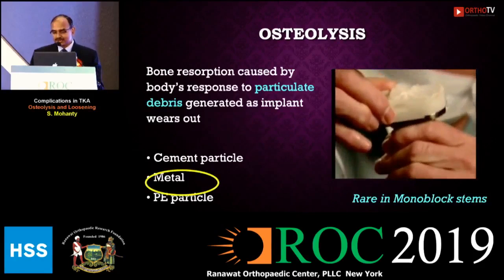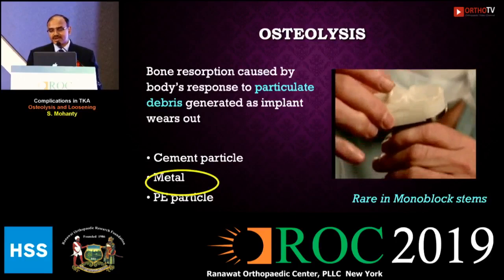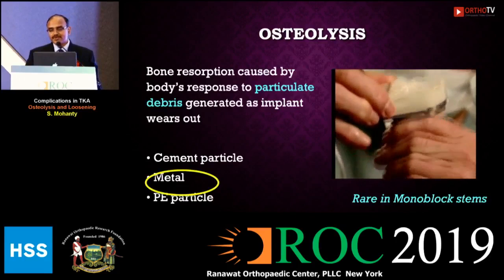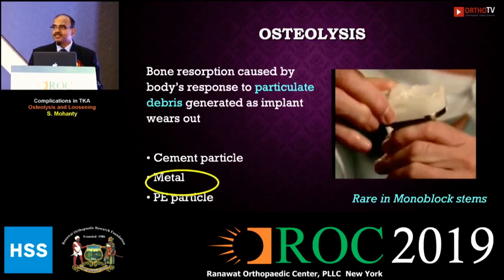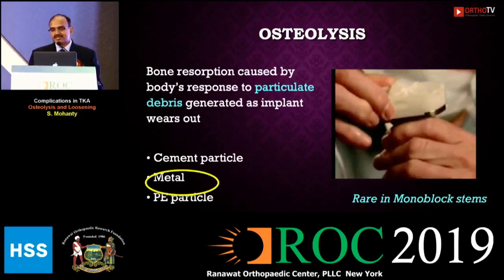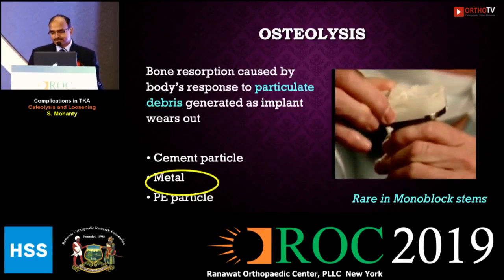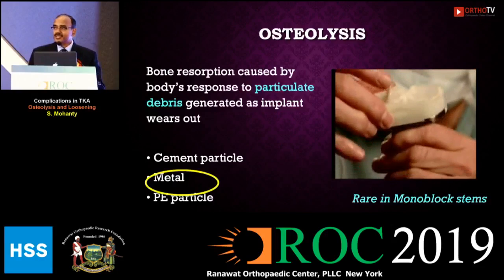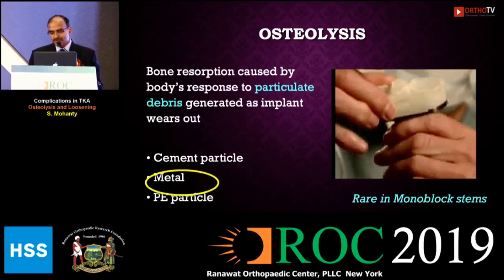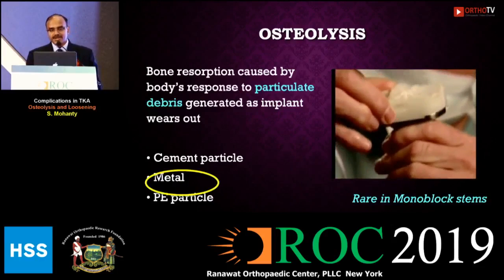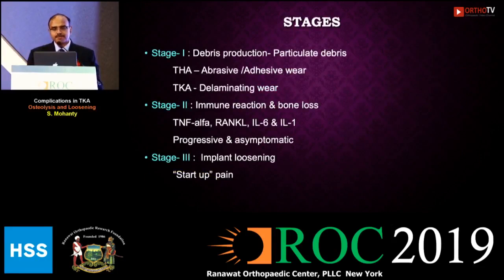Polyethylene particles are generated because of under-surface wear in modular components. The particles generated between the metal and polyethylene are much smaller in size and hence give rise to osteolysis. That is why it is rarely seen in monoblock implants like all-poly tibia or monoblock metal-backed tibia.